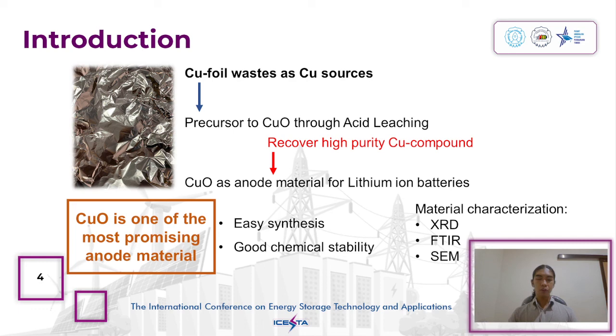The waste from copper foil can possibly be used as a source of copper. The material is easy to be converted to copper oxide, one of the most promising anode materials for application in lithium-ion batteries due to the easy synthesis and good chemical stability. Copper foil from spent lithium-ion battery cells was used as a precursor to copper oxide. A simple hydrometallurgical approach, specifically acid leaching, was used to recover high purity copper compound. The obtained copper-based compound was characterized using XRD, FTIR, and SEM.